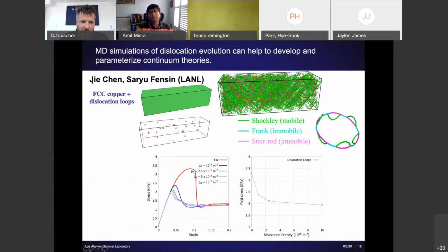where these calculations were performed by Jie Chen, a postdoc working with Saryu Fensin in MST here at Los Alamos. And so they're looking at simulations of the evolution of, in this case, copper during compression when you start with a certain number of dislocation loops. But the material is relatively pristine. Within this box, we can see the dislocation loops, but there's no real impediment. And if we increase the dislocation density from this state, all we're doing is increasing the availability of mobile dislocations to accommodate the plastic flow, so that what we observe is that the imposed stress versus strain softens as you move from a lower mobile dislocation density to a higher mobile dislocation density.